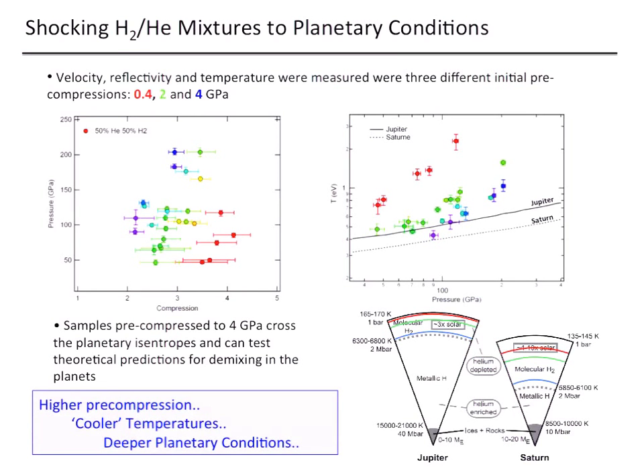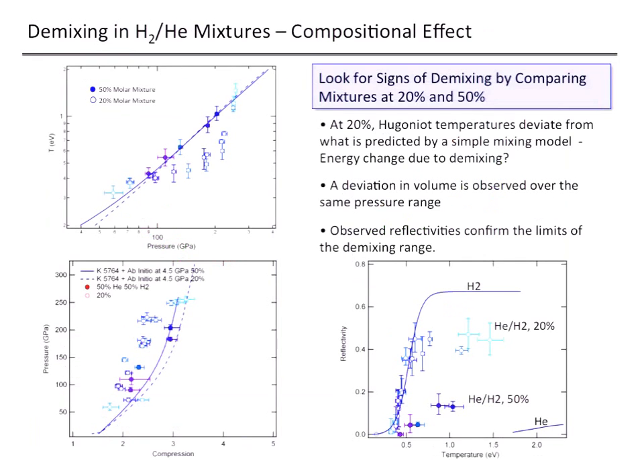These experiments at the lowest temperatures and highest pressures are directly accessing planetary interior conditions. These colors here schematically show where red and blue fall in Saturn and Jupiter. In Jupiter we're still just scratching the surface because it's a huge planet—the core is somewhere around 40 megabar probably. But in Saturn, we're getting down into this interesting region where we might address these demixing problems. So with higher pre-compression, we get to cooler temperatures and deeper planetary conditions.